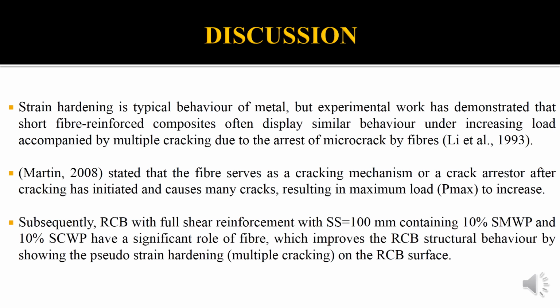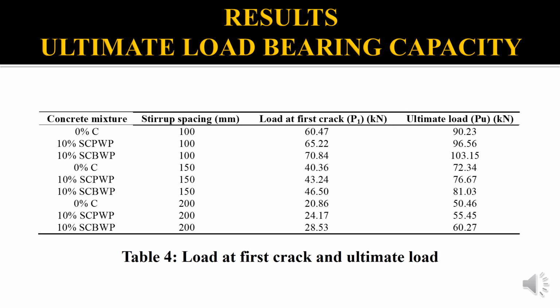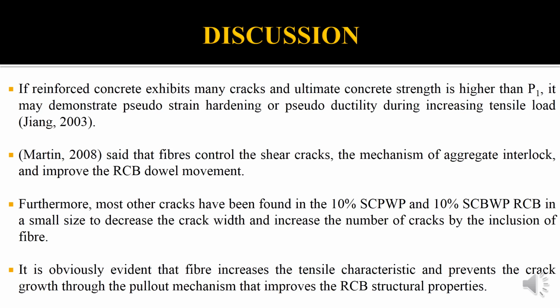Subsequently, the reinforced concrete beam with full shear reinforcement with stirrup spacing 100 mm containing 10% shredded copier waste paper and 10% shredded cardboard waste paper shows a significant role of fiber, which improves the reinforced concrete beam structural behavior by showing pseudo-strain hardening and multiple cracking on the beam surface. Table 4 shows the load at first crack and ultimate load. From the table, 10% shredded cardboard waste paper with stirrup spacing 100 mm records the highest load at first crack and ultimate load values.